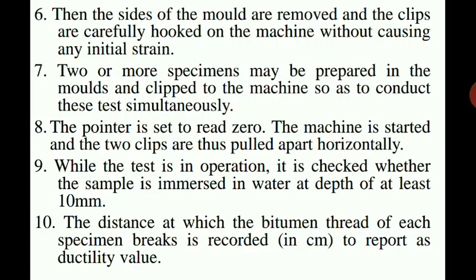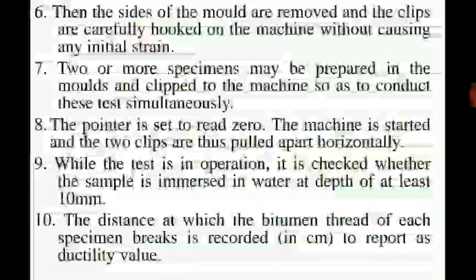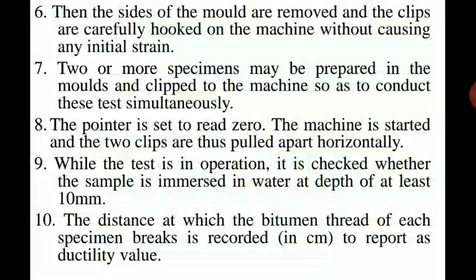While the test is in operation, it is checked whether the sample is immersed in the water at a depth of at least 10 mm. So here we need to maintain a minimum of around 10 mm of water, so that the water level crosses that particular mold stage. So that means we can conduct the test in the water bath, so that no other disturbance will affect the results.